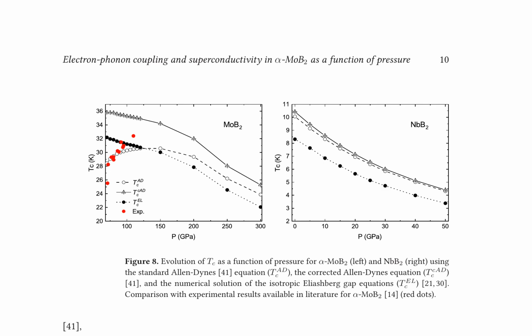A key aspect of this analysis is the comparison with experimental results for alpha MoB2, which reveals significant differences in superconducting temperature estimates between strong coupling schemes and the standard Allen-Dynes equation. Notably, in the low-pressure region, alpha MoB2 exhibits strong coupling behavior, leading to discrepancies between the estimates.